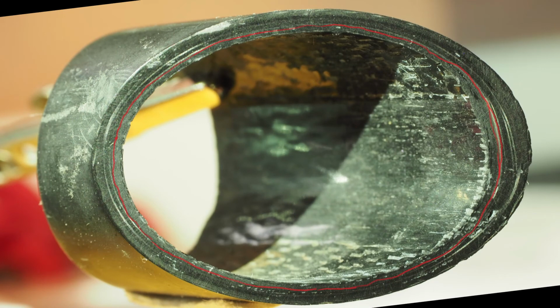On closer inspection under the microscope, the material on the inside of the red line shown here is actually glass fibre composite. Outside the red line, it's carbon fibre. The glass fibre is primarily unidirectional, with the strands running down the length of the seat pin. However, around part of the inside there's also a section of woven fabric.